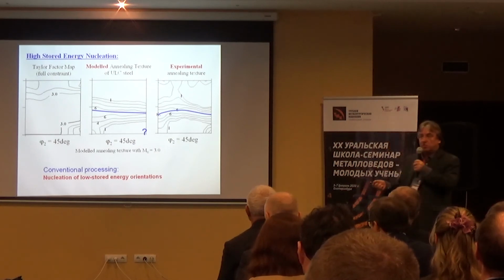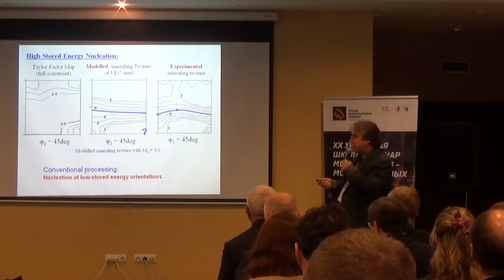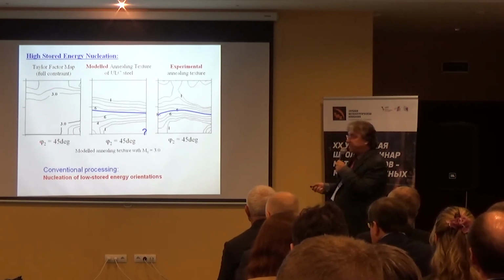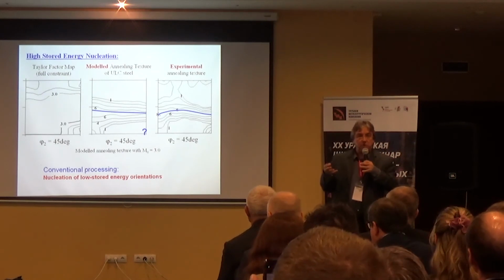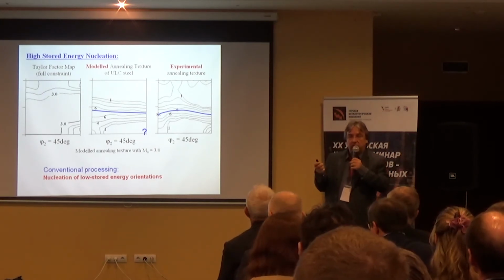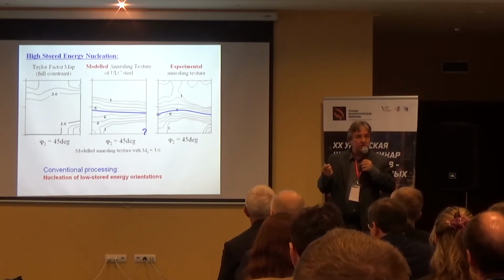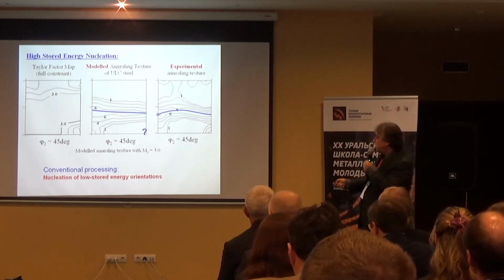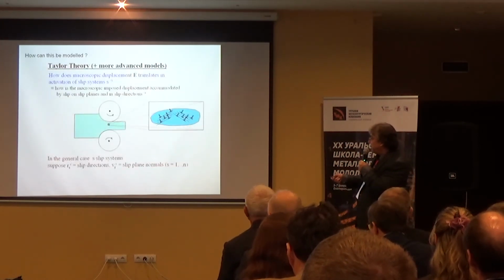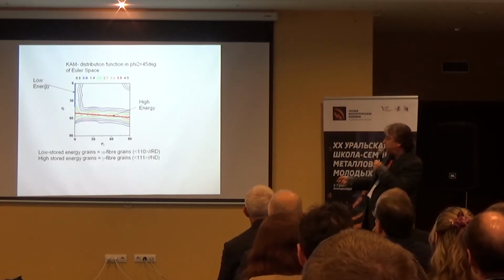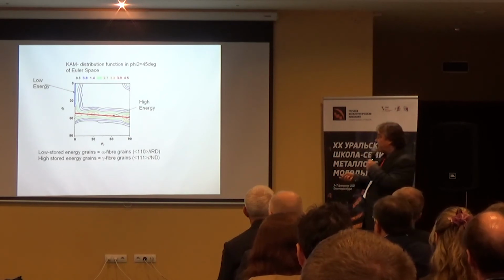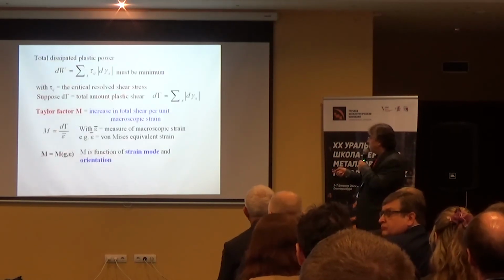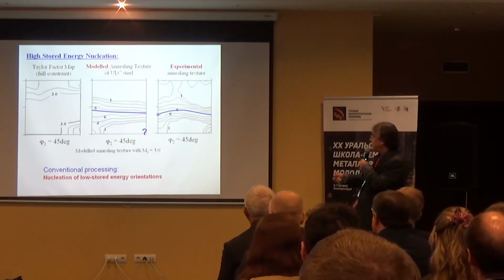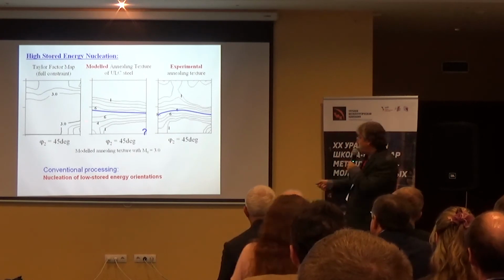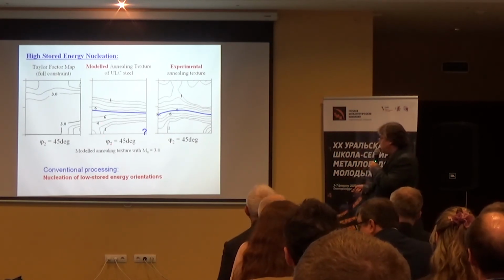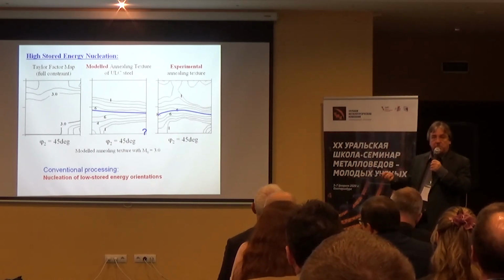And then we can use this to have a model of the recrystallization texture, because suppose now that we filter out only the high stored energy. Suppose that we assume that only orientations with high stored energy can recrystallize, the ones with the highest driving force. So if from this experimental deformation texture you filter out all of the orientations with the high Taylor factor, that's what you get. You see? This is the gamma fiber texture, which also spreads onto the rotated cube component. So this can be the basis of a recrystallization model.